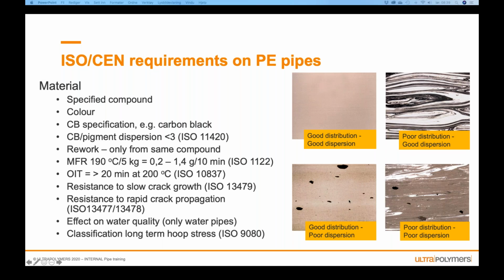If you look at the lower left, the extruder is working very well. So it's distributing the master batch very, very well. But the carbon black master batch you are using is not good. You have a too big variation in the size of the carbon black in the master batch. And the final picture, lower right, is when the carbon black master batch and the extruder are both poor. So this is impossible to see if you don't do microscopy analysis on it.